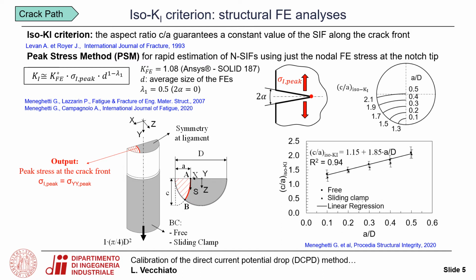As a result, it was possible to obtain the crack path, the aspect ratio c over a versus the normalized crack depth, which corresponds to the ISO K1 criterion. And it was also observed that it was almost the same for the two studied boundary conditions.